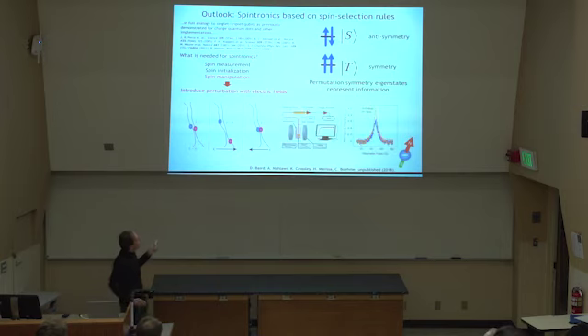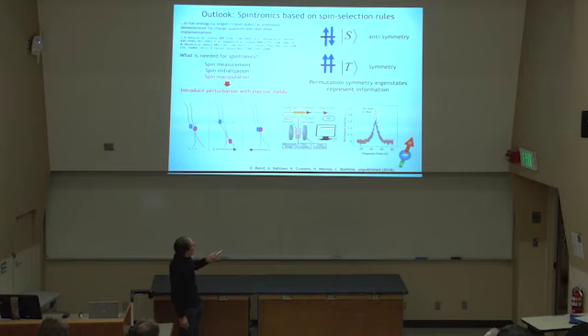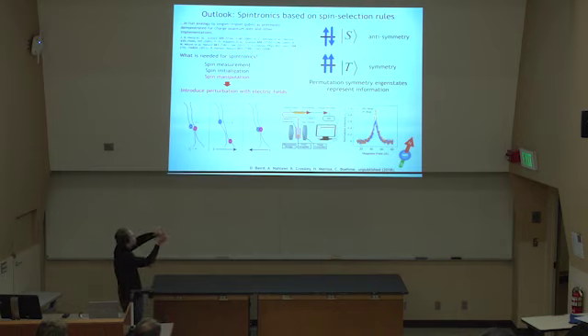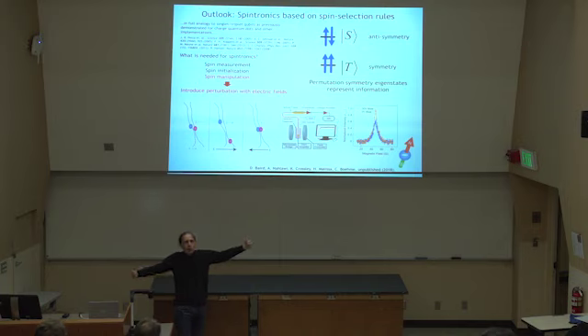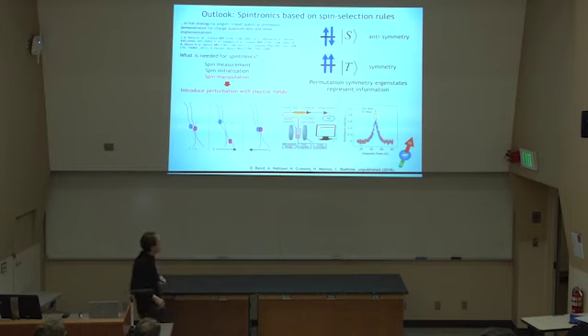What gives us hope that we're not completely off is if you apply electric fields to these systems and then look at these spin-controlled currents, you get really strong changes of these signals. So your rate on resonance, essentially your current change due to magnetic resonance, is quenched by 50%, by half. And that's consistent with randomly oriented pairs where half of them you pull apart due to the random orientation, whereas the other half you pull closer together, and therefore you cut out half of your electronic transition rate.